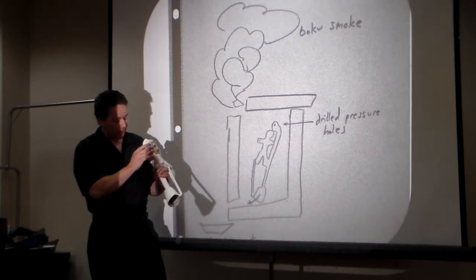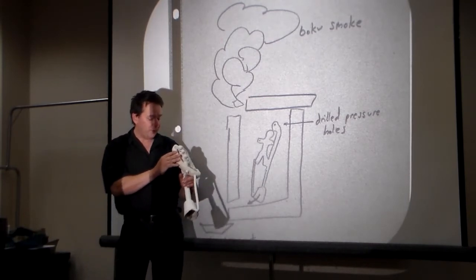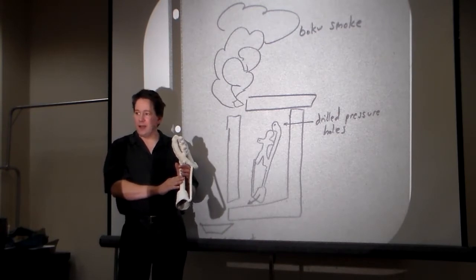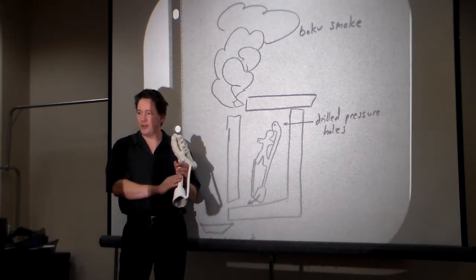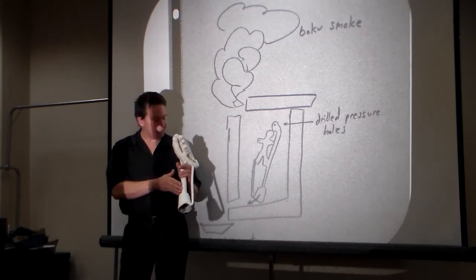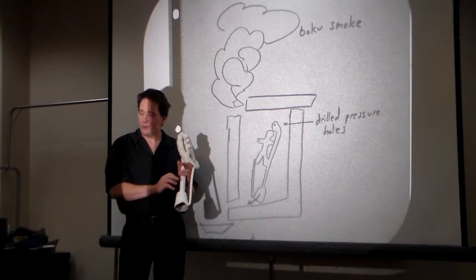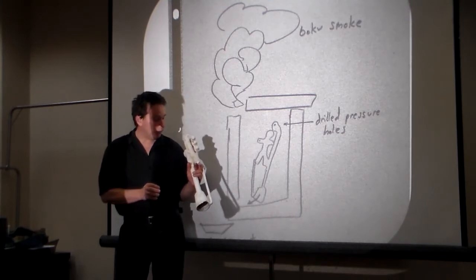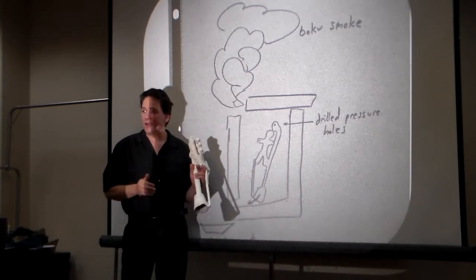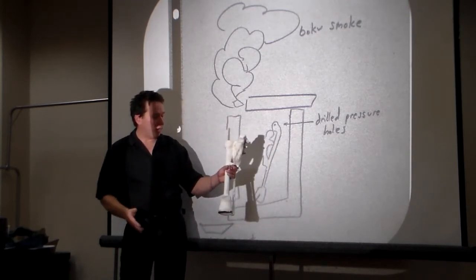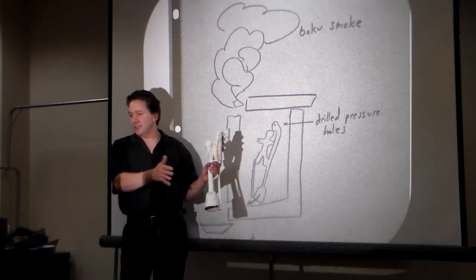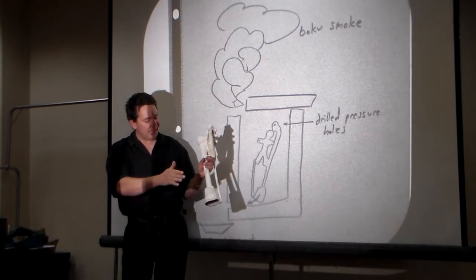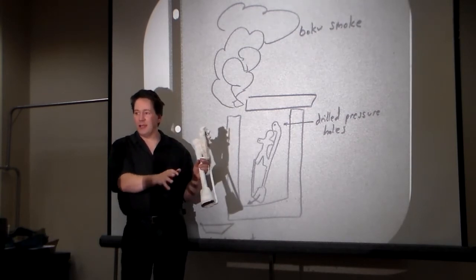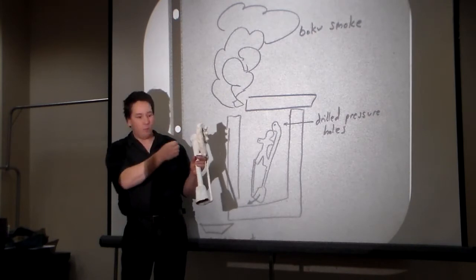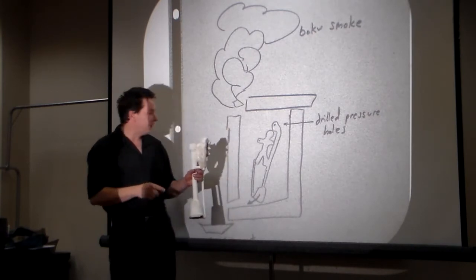One of the issues with ceramic, and also with the other methods, is that wax will expand during the burnout cycle, and the ceramic doesn't fire to its hard strength until well above the temperature of that melting wax. So there's a risk of the shells cracking when we go in to burn the wax out. To deal with that, we have the temperature so high. The outside surface of the ceramic is going to fire and harden before we even start to melt the wax. And because of that super fast heat, the outside surface of the wax will melt away before we start warming and expanding most of the wax on the inside of this piece. That's how they do the burnout for ceramic.